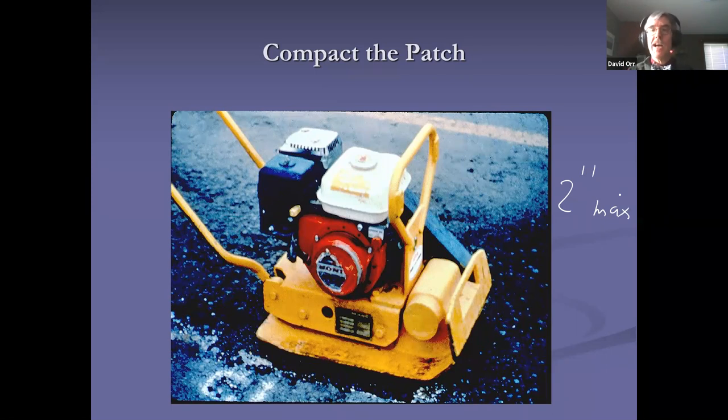And if that's what you've got, do that. Don't hit it with the silly hand tool. The hand tool's doing even less. The vibration tool at least gave you a couple of inches' worth of effort, okay? So if you had to do 4 inches and that was your tool, well, okay, do a couple of quick lifts. It doesn't take that much extra time. Do the lift, hit it a couple of times, scarify it real quick, do a second lift, that gives you your 4 inches, okay?